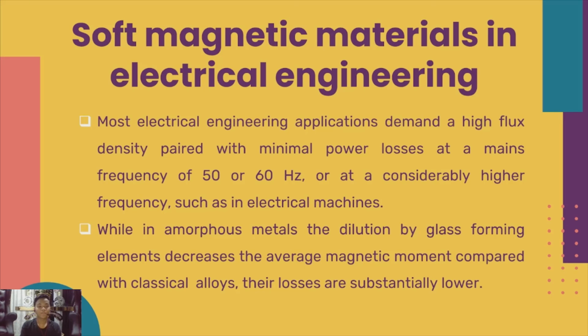Okay, the second result is soft magnetic materials in electrical engineering. Most electrical engineering applications require a high flux density paired with minimal power losses at 50 or 60 Hz mains frequency or a significantly higher frequency. While in amorphous metals the dilution by glass-forming elements decreases the average magnetic moment, compared with classical alloys, their losses are substantially lower. This has been the primary influence of amorphous metals, notably their usage as alternate core materials in distribution transformers.